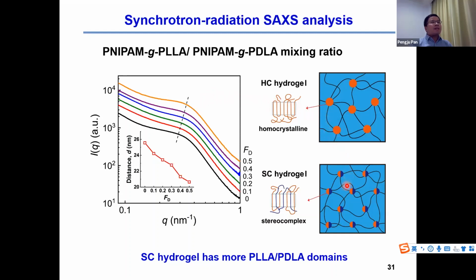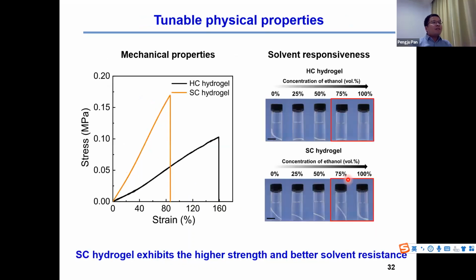Compared to the homo-crystallization physical gel, the stereocomplex hydrogel has a higher density but smaller size of hydrophobic domains. This means the stereocomplex crystallization has a better physical cross-linking effect on the hydrogel. Therefore, the stereocomplex hydrogel is more rigid than the homo-hydrogel. It has a larger strength and modulus, but lower flexibility.